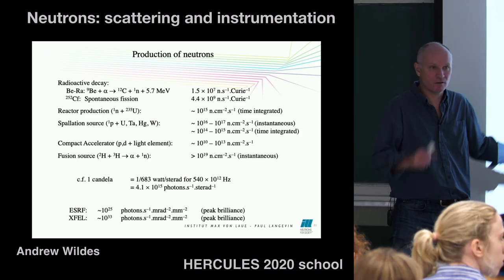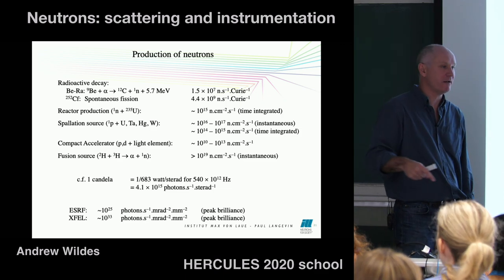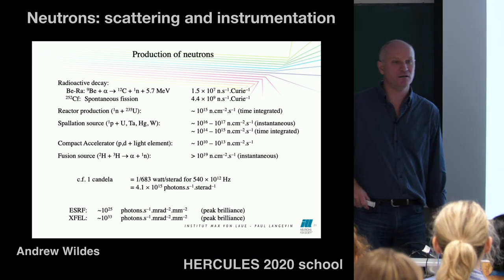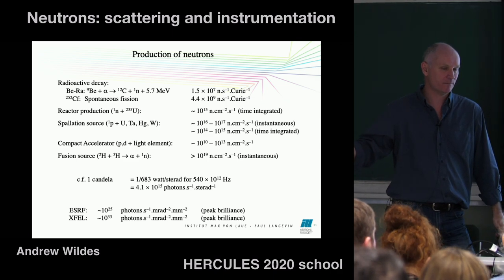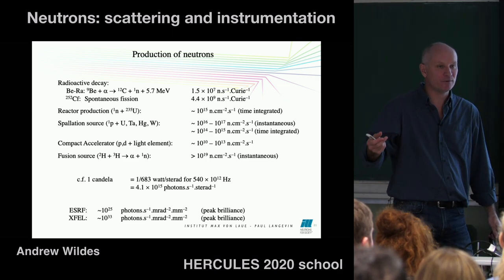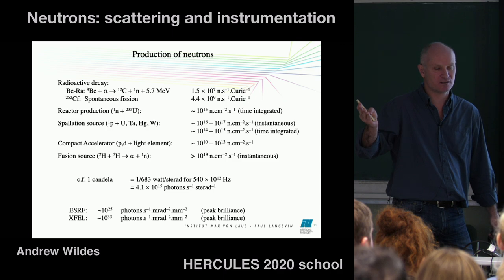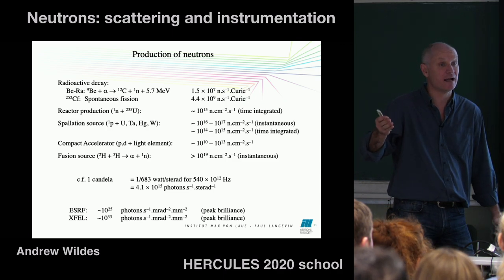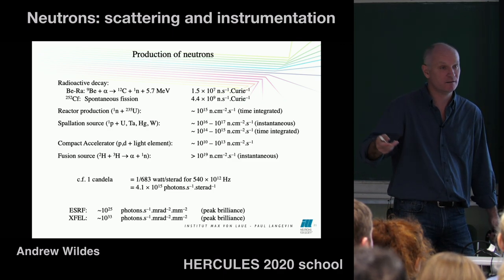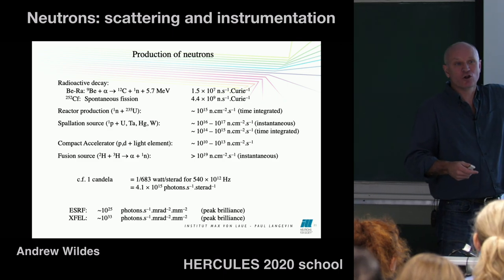Your reactor produces of the order of 10 to the 15 neutrons per centimeter squared per second. By the time you get to your sample, you might have of the order of 10 to the 6, maybe 10 to the 8. It depends. So you've already lost a lot on top of this.